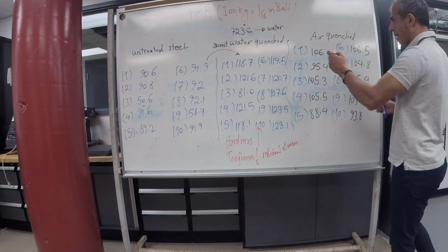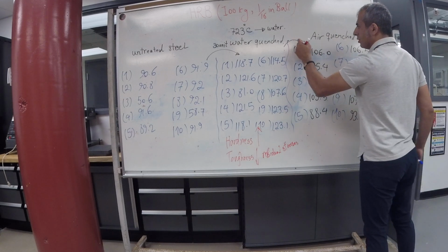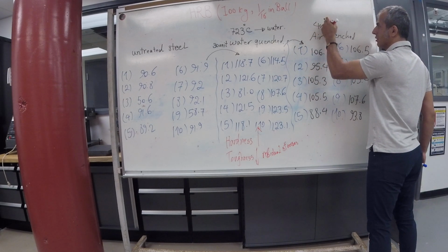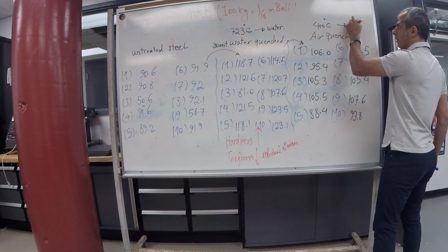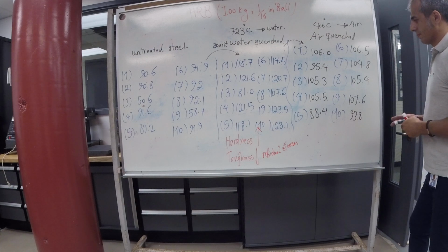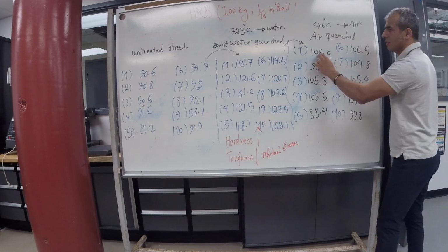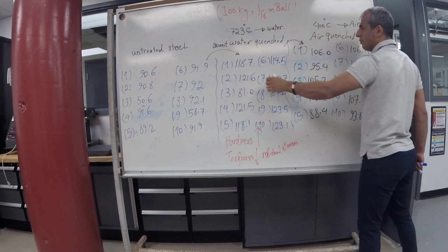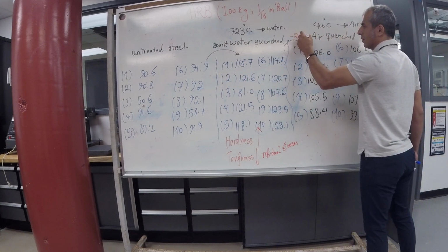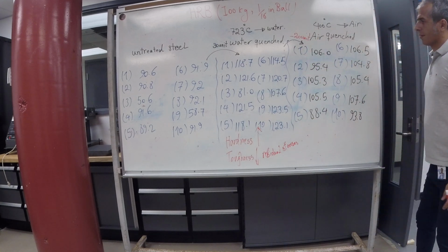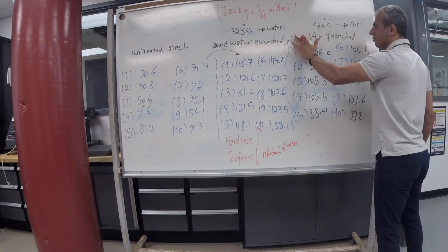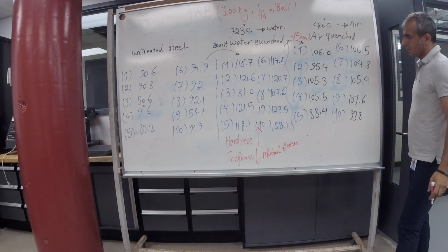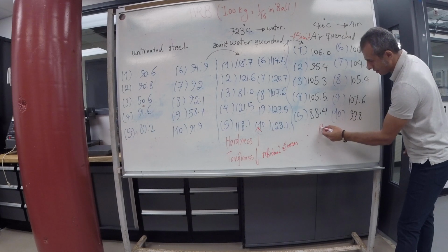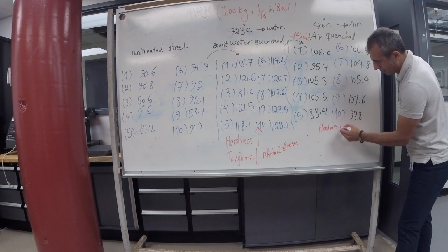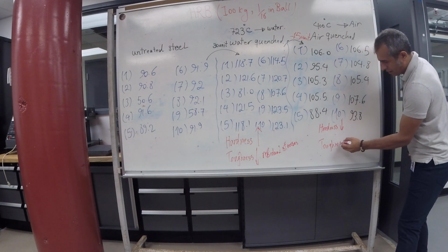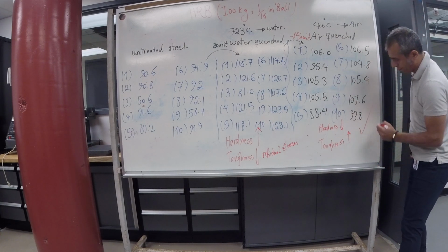So then I again, this sample, I heat it up to 400 degrees Celsius and air cooled. So as you can see, the value is less than this, but greater than this. 10 unit less than this, average minus 20 unit. Or 10, 15, let's say. But hardness sacrificed a little bit, toughness increased. So this is what we are looking for.